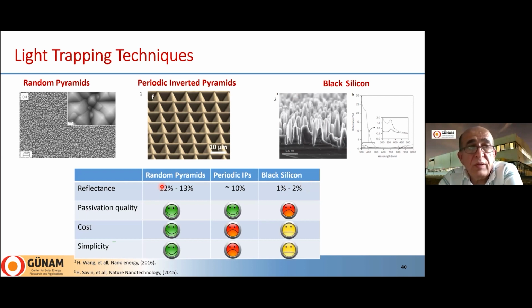Okay, when we compare these three approaches, we see that random pyramids are always good. We have good passivation, good cost, and simple. The other two techniques are not that attractive, even though we have very good reflectance. Black silicon reflectance can be down to 1 or 2%. The inverted pyramids reflection can be down to 10%.